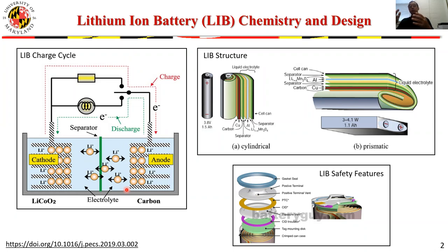Now, these reactions, both the reaction of the lithium with the electrolyte and the decomposition and reaction of the cathode with the electrolyte, do not occur at room temperature because those reactions have a non-zero chemical barrier. So there is an activation energy that is required to be overcome for these reactions to occur. At room temperature, the system is stable, which is what makes it possible for this battery to operate normally. But if you increase the temperature of that system by about 100 degrees C or so, those reactions start to take place. And once they start, as I already mentioned, they produce a considerable amount of heat and heat the media of the battery.